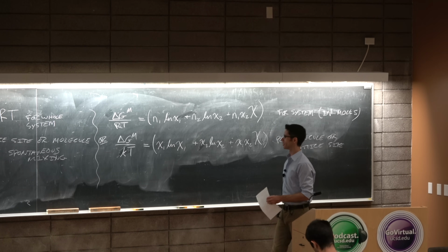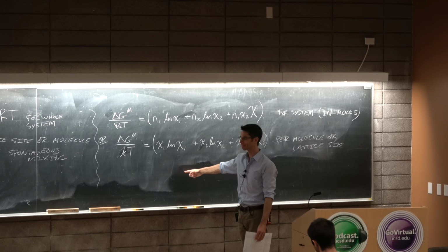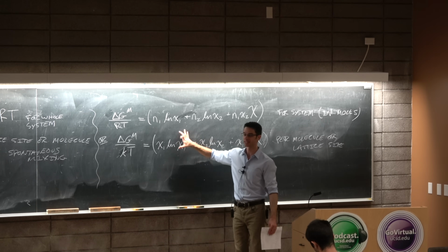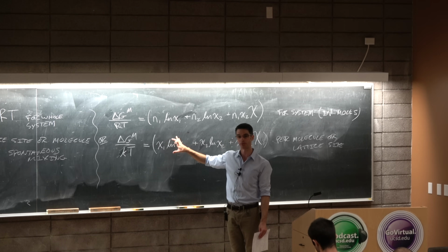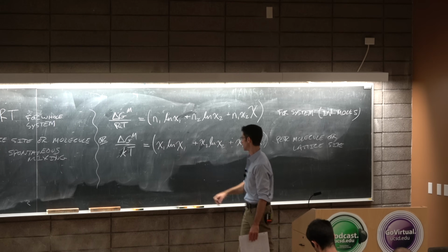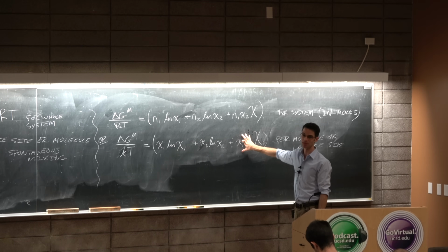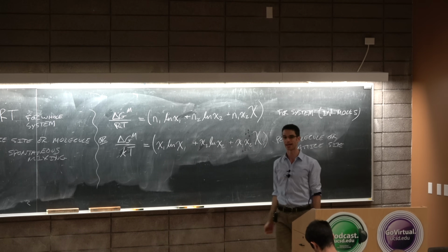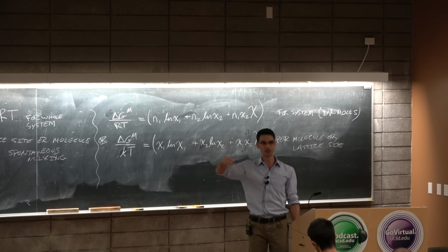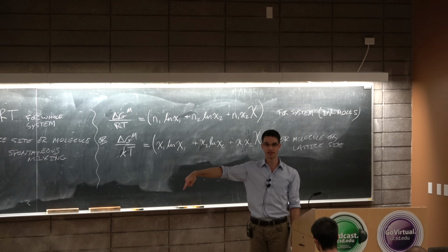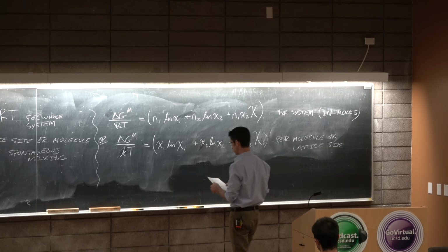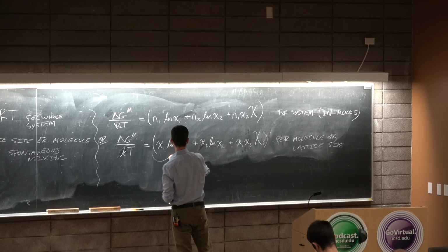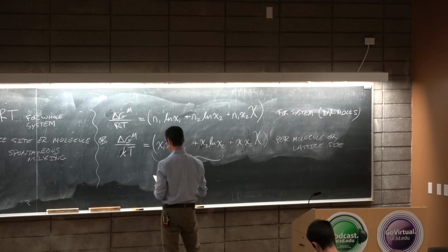Okay, so we boiled this down to pretty much what we had last time, where we can make the appropriate substitutions for polymers in terms of big N's and phis from the Flory Huggins entropy, which we'll do at the beginning of class next time, plus this enthalpy term. This enthalpy term came as a result of the fact that exchanging 1 and 2 into each other's business gives you a non-zero change in enthalpy because the intermolecular forces are different. So this is the combinatorial term.